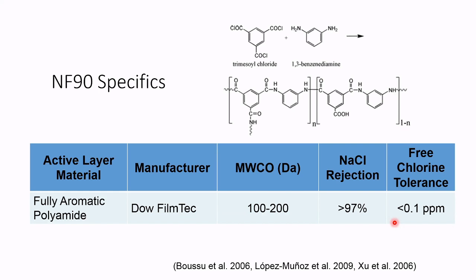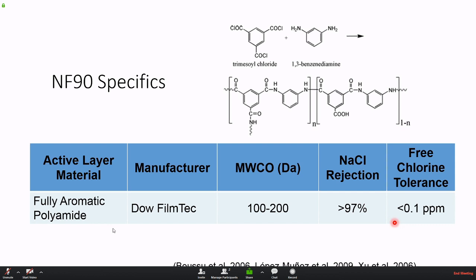So the membrane that we selected to begin with is an NF90 membrane, and they are, just to remind you, the fully aromatic structure, trimesoyl chloride reaction with 1,3-benzene diamine, also known as MPD. That's the structure of the membrane that we use for these studies. Molecular weight cutoff means anything that's above a molecular weight of 100 to about 200 is typically rejected. That's how tight the filter is. The NaCl rejection, or sodium chloride rejection, is greater than 97%. And the free chlorine tolerance, remembering that these membranes are sensitive to chlorine, is less than 0.1 ppm.